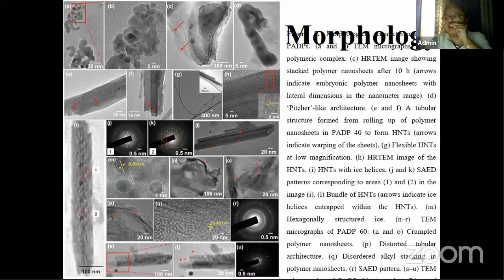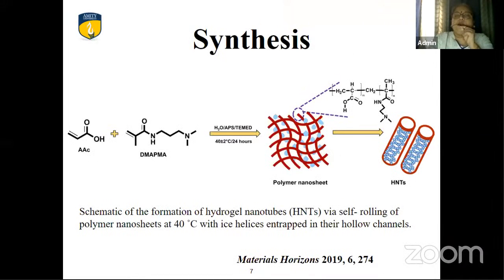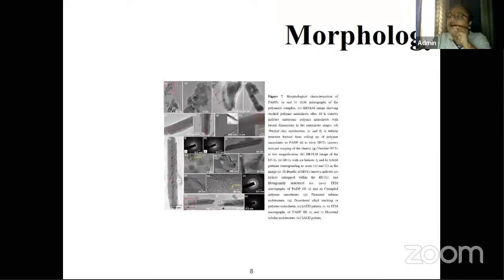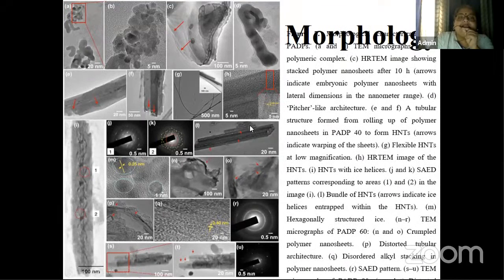Now, 2D polymer nanosheets with hexagonally structured ice locked into the polymer mesh were obtained by a free radical aqueous copolymerization. Just to go back, free radical aqueous copolymerization, which I told you. In due course of time, the alkyl side chains revealed unique interdigitated packing. See, the alkyl side chains are going for the packing of the material. The sheets are rolling. So what is the mechanism of rolling of the sheets that we have given? The alkyl side chains reveal unique interdigitated packing in a confined geometry, and the crystallization pattern forms a hexagonal rotator phase stabilized by nanoscale confinement. Furthermore, at a particular temperature, the sheets buckle out of the plane into crystalline hexagonally packed HNTs. So these are the sheets which buckle out to form the hexagonally packed HNTs, that is, the hydrogel nanotubes.